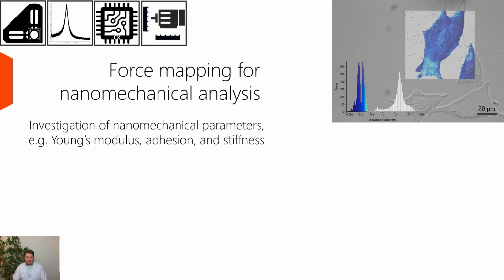I showed a lot of imaging applications by now, but there's also other things that we can of course do, and one of them is force mapping, force spectroscopy using the AFM. And this is often used to investigate mechanical parameters like the Young's modulus, adhesion, or stiffness. The example that you see up here is a force map taken on live cells at 37 degrees in cell culture medium. And you can see here the elastic modulus plotted on top of the cells. And you can see here the histogram of the elastic modulus distribution on those cells. And this white part here corresponds basically to the glass surrounding of the cell, of the petri dish.